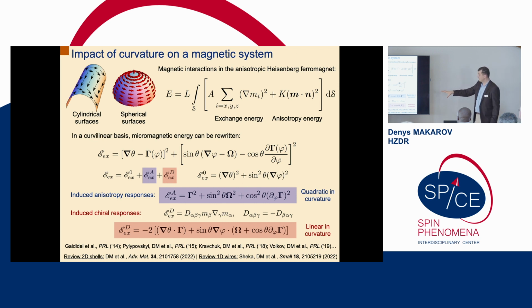That you will have eventually your thin film, which you geometrically curve, will behave as if it has additional anisotropy and Dzyaloshinskii-Moriya interaction. So this is a relatively straightforward thing, because when you do a geometric transformation, you simply take a tensor and transform it. It has nothing to do with physics, right? It's basically a coordinate transformation. If you have spatial derivatives, you will necessarily have a geometric potential and a scalar potential. In different fields, these two potentials are called differently. Like in magnetism, we call them Dzyaloshinskii-Moriya and anisotropy, okay?